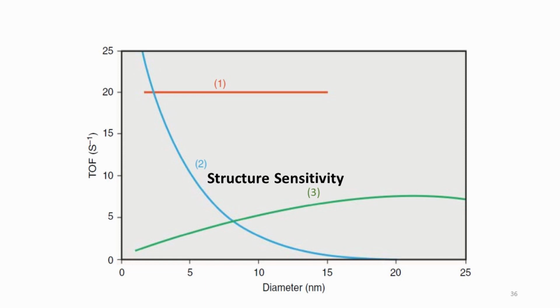One of the most important classifications of heterogeneous reactions is the one that divides them into structure-sensitive and structure-insensitive reactions. In structure-sensitive reactions, the turnover rates per surface atom of the catalyst depend on the size of the catalytic particles. For structure-insensitive reactions, every surface atom is equally active. Single crystal studies have clearly shown that the rate of such reactions, for example ammonia synthesis, strongly depends on the structure of the metal surface, while alkene hydrogenation has been found to be insensitive to surface structure.